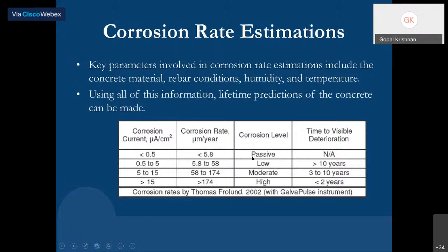So that is the low level of corrosion, it is greater than 10 years. Then 5 to 15 microampere per centimeter square, 58 to 174 micrometer per year corrosion rate is going to happen. Then it is considered moderate. It is 3 to 10 years.